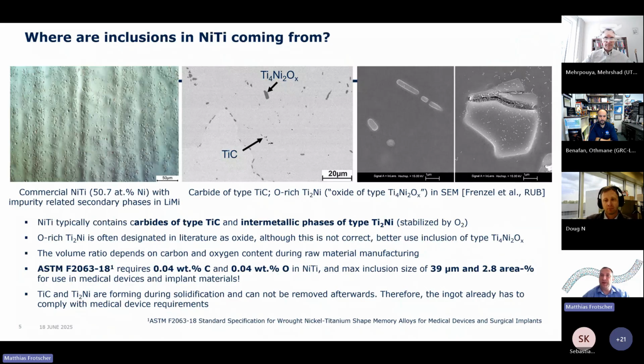Now moving on to the new standard test method on porosity and inclusion analysis of Nitinol. Where are the inclusions actually coming from? First of all, the alloying elements, nickel and titanium, can already contain impurities, but the majority of the carbon and the oxygen we have in the alloys are coming from the melting process. This is also the reason why we have to use vacuum methods to reduce the amount of oxygen as much as possible, and what makes the processing expensive.